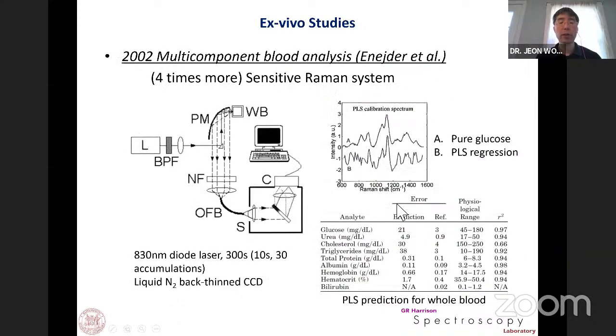So coming back to the laboratory, the issue of Raman spectroscopy has always been that the signal itself is too small. So instead of using a high NA objective lens, this time we used a paraboloidal mirror. By using the paraboloidal mirror, we could increase the system throughput by 4 times. And with this improved high-throughput system, we could measure glucose, urea, cholesterol, and other analytes from whole blood. We used partial least squares calibration algorithms. This is the regression vector, and this is the glucose concentration, the reference glucose signal from the glucose solution. You can see our PLS model is predicting the glucose changes.